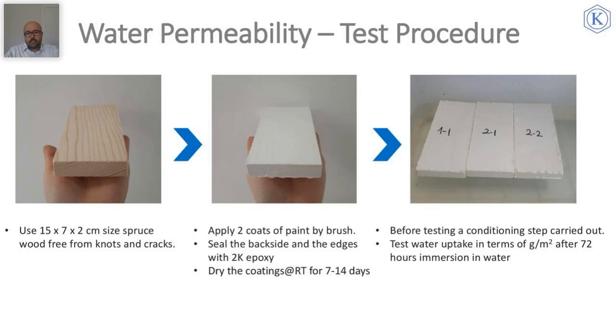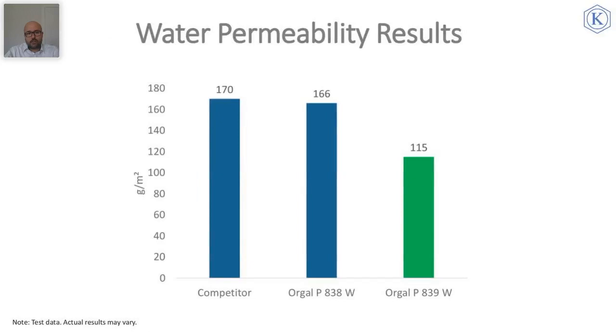This test is very critical, and it is a must in certain areas in Europe for the quality criteria of wood coatings. And the EN 927 norm is asking for water permeability results below 175 grams per meter square. As we see in our test, of course, this test is very dependent on the paint formulation you are testing, the amount of application, type of the wood, porosity, etc. But we know 838 is also fulfilling those requirements in many formulations.